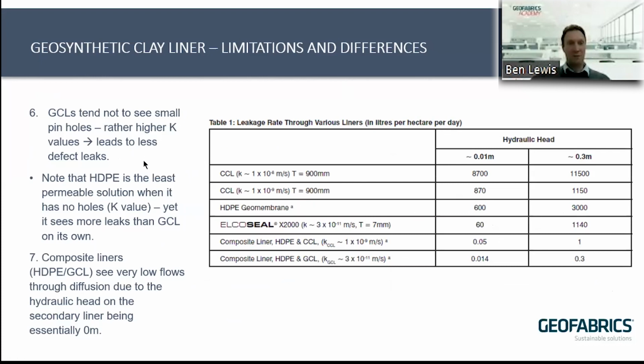GCLs tend not to see as many small pinholes because once they hydrate, they'll swell up and fill those voids. So you tend not to get as many defects, but you will see a higher hydraulic conductivity value. HDPE is the least permeable solution when it has no holes because it has a very low hydraulic conductivity, yet it can often see more leaks than GCL when it's on its own due to the risk of defects during installation. So there are things like that you need to consider, and that's why GCLs really should be protected.